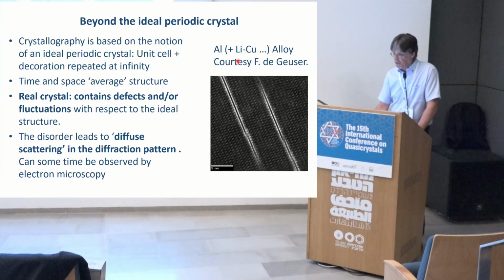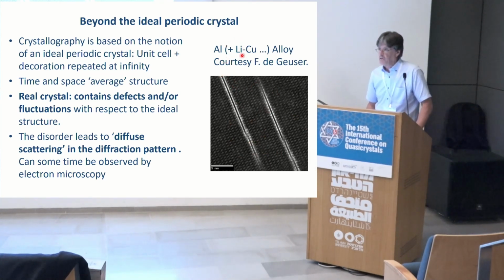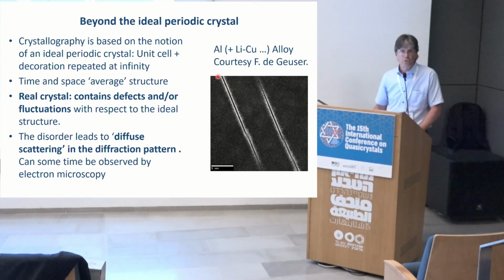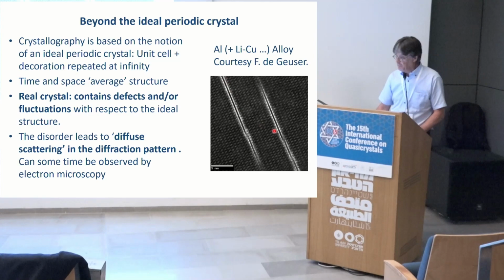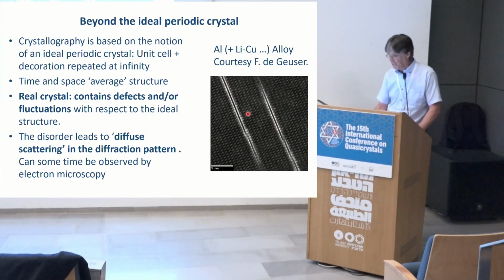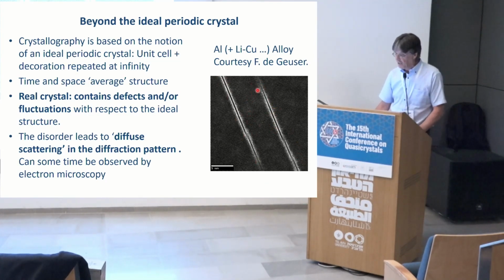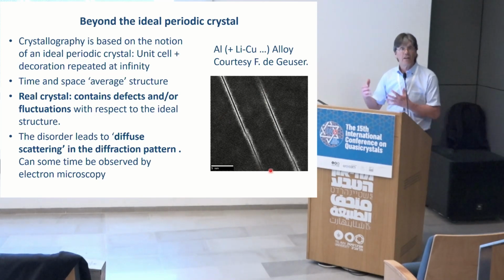I'm just showing here an example taken from metallurgy. This is a light aluminum-lithium-copper alloy used in aeronautics for Airbus, and you have these precipitates, which are defects. Nice arrangement in between, but these precipitates are key in having the properties of your material. And this disorder, or defects, creates what we call diffuse scattering in the diffraction pattern.